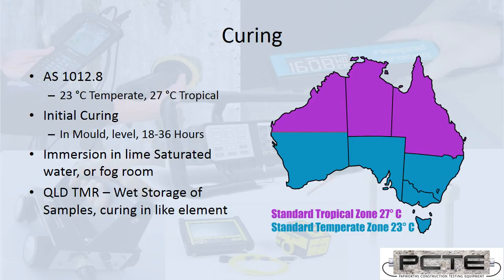The curing environments in Australia are defined by where in the country we are. In the temperate zone, it's a 23 degrees centigrade curing environment, and in the tropical areas, it's a 27 degrees standard curing environment. The other thing that's defined here is an initial curing period, minimum 18 hours, no more than 36 hours, where the cylinder is cured inside its mould, covered to protect from moisture loss, but not in a moist or immersed environment. Once that period is complete, the cylinder needs to be transferred as quickly as is practicable into a moist curing environment.